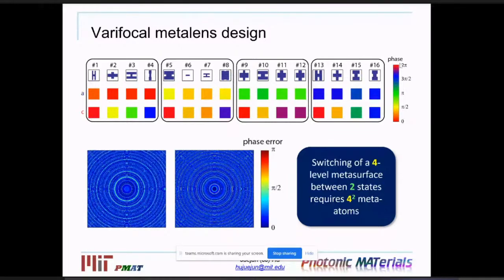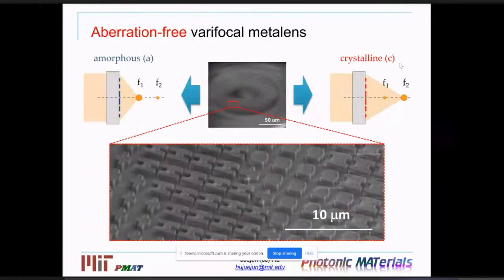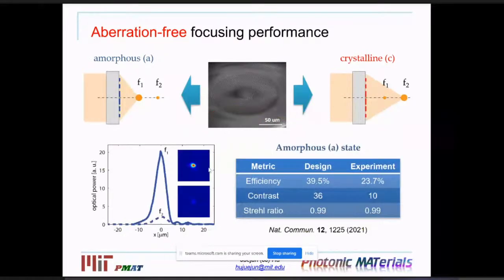So using this approach, we can now create essentially arbitrary wavefronts in the amorphous and the crystalline state and realize binary switching between arbitrary photonic functionalities. Of course, we can use that to create a bifocal metalens that switches from one focal spot to another focal spot. We then fabricated this metalens using our GSST phase change material.